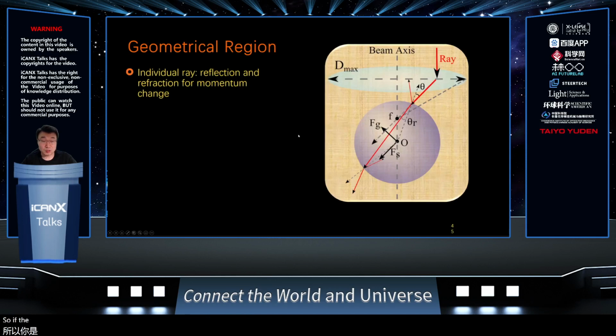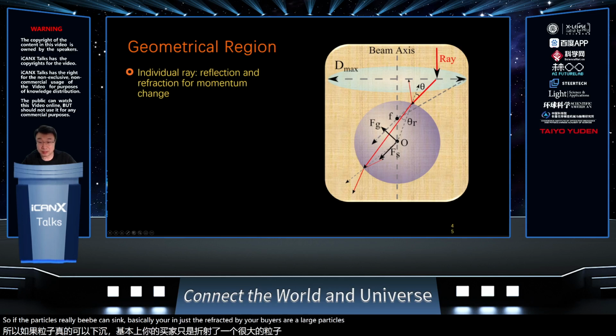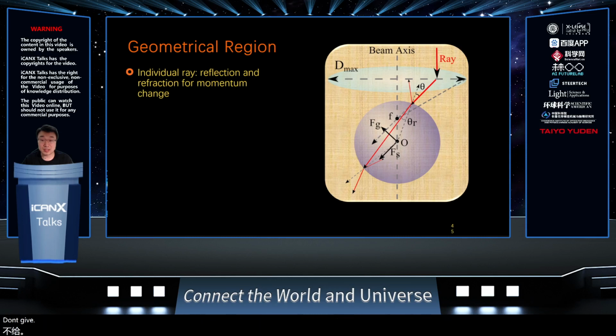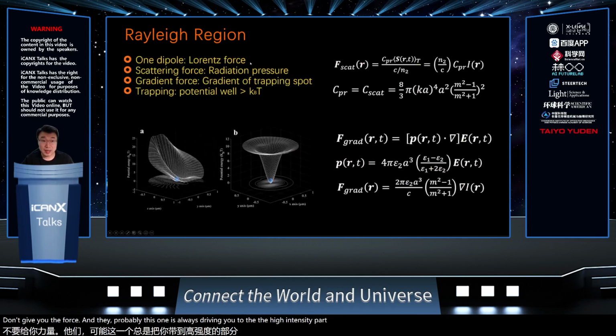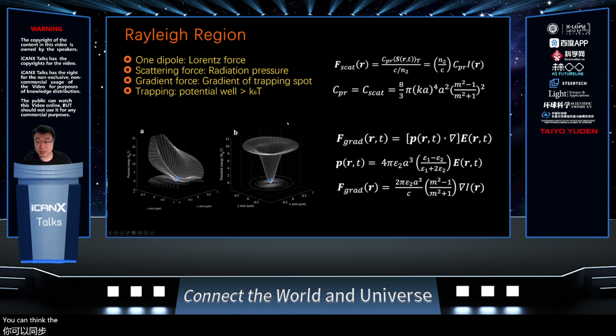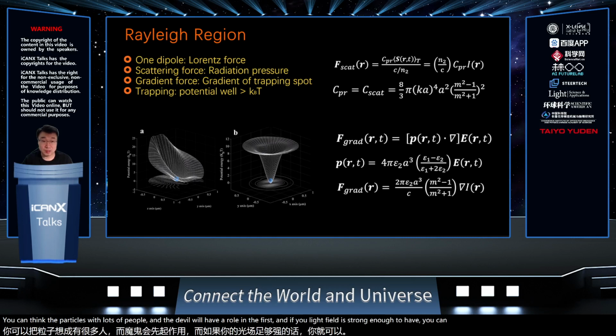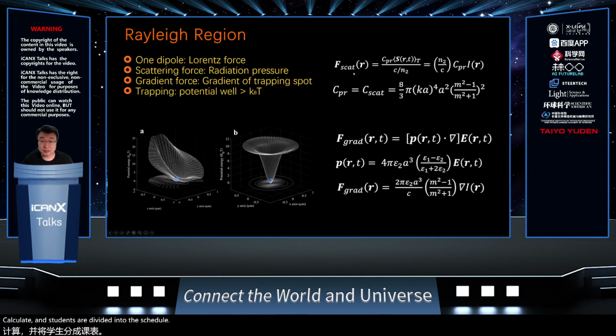If the particle is really big, you can think of your beam as just refracted by your large particle sphere, and any redirection of the laser beam basically has a momentum change, and this momentum change is going to give you the force. If you calculate this, it always drives you to the high intensity part. And if the particle is really, really small, it falls into the Rayleigh range. So this is the nanoparticle. For that one, you can think the particle is just a dipole, and the dipole will experience a Lorentz force. If your light field is strong enough, you can calculate and divide this into the scattering force and the gradient force. The scattering force is basically the radiation pressure pushing the particle away, and the gradient force forms a potential well, and the particle will go into the bottom of the potential well.